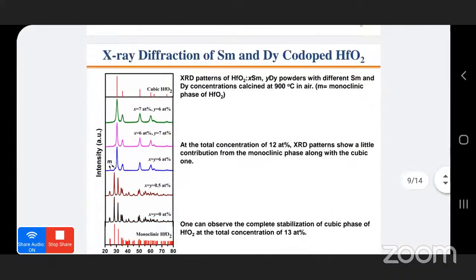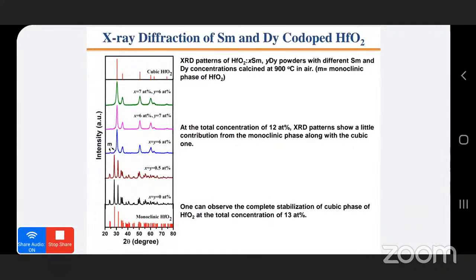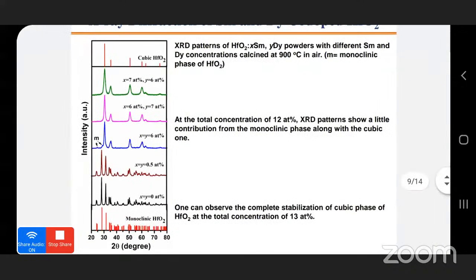We have further studied the co-doped system, since we can utilize it in different fields also. That's why we thought of examining, if we co-dope samarium and Dy, how the dopant concentration varies to stabilize the cubic phase. For the pure system, the hafnia is monoclinic in nature, but as we increase the concentration of dysprosium and samarium, both at 6 atomic percent, giving a total concentration of 12 atomic percent, we can see that along with the cubic phase, there are two very small contributions from the monoclinic one. So at 12 atomic percent, whether we take samarium or dysprosium as 6 atomic percent, both the monoclinic and the cubic phase of hafnia exist at room temperature.